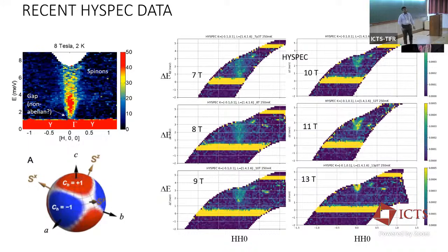Kiran is my first graduate student to join me when I joined Purdue, and with her we have been taking some of this data set. This is the data that we took at HYSPEC, at 7.3 Tesla, 8 Tesla, 10 Tesla, 11 Tesla, 12 Tesla, and 13.5 Tesla. What we find is that we don't see any magnons right here. It's basically a cloudy scattering spectrum, which is completely deconfined. And it remains that way almost until 10 Tesla, which is where you start to see this magnon-like feature appearing.